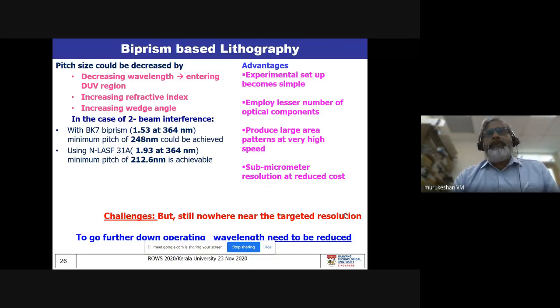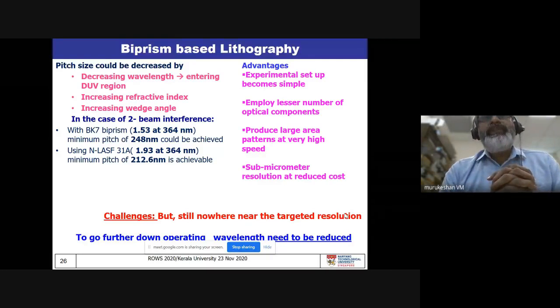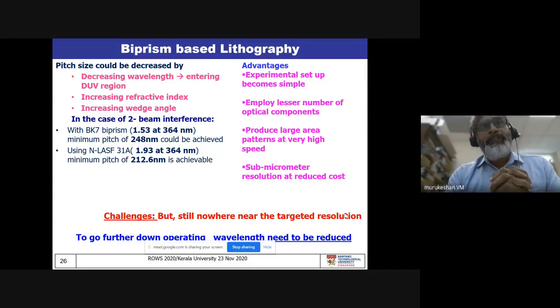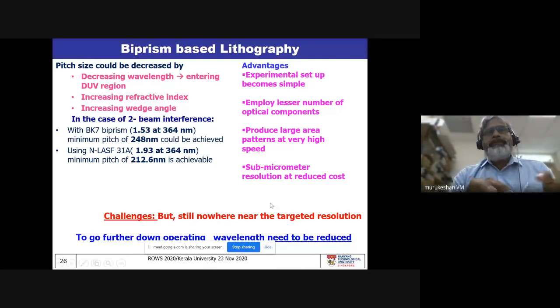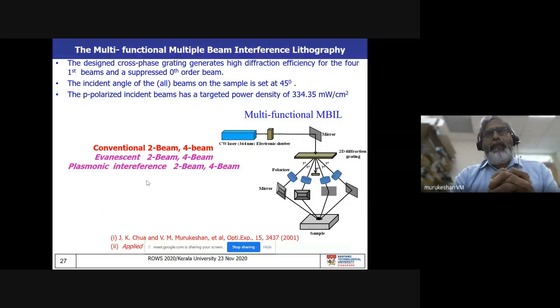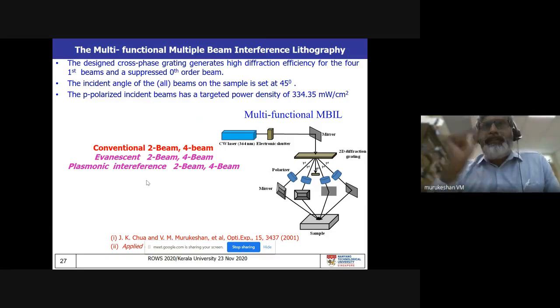So what do we have to do to achieve the targeted nodes, the feature size that we have been given, that is sub 30 nanometer? We tried to do all those things. We tried to increase the prism refractive index, but all of that took us only to around 212 nanometers. So we found that it is really challenging using such approaches. So we thought, why can't we use the other, amplitude-splitting-based approach? The advantage of the biprism-based approach is that you can get very large area patterning, so beautifully patterned, and it has very many applications, but not the application that we intend to start with.